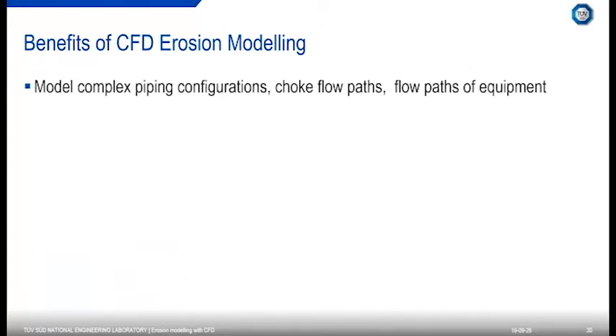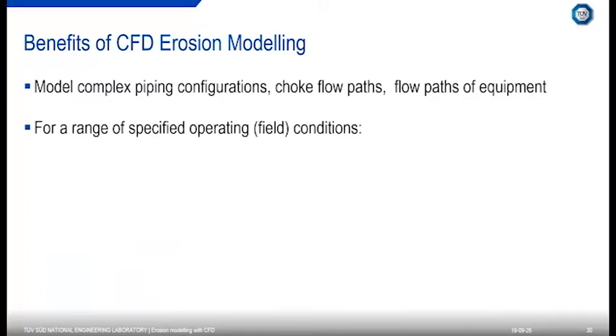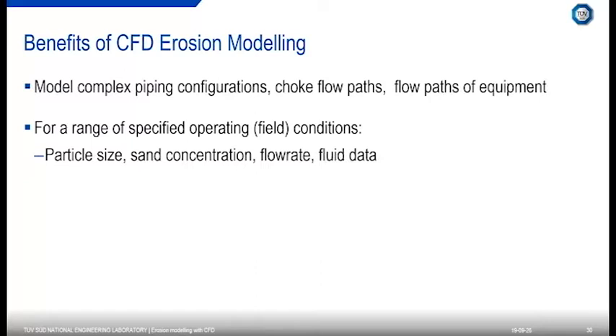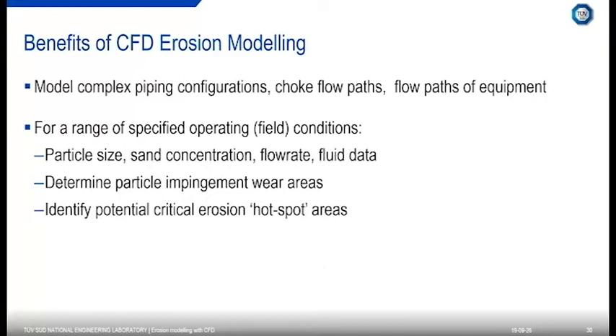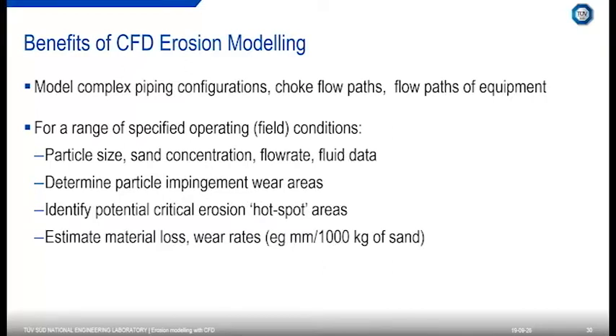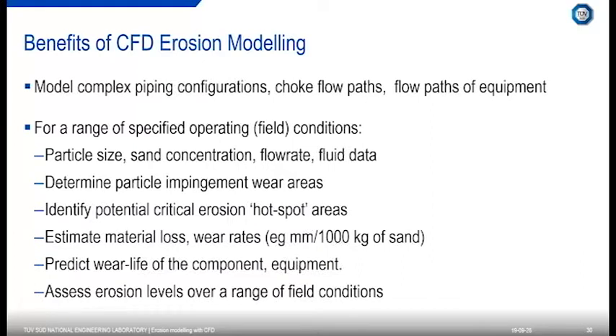So the benefits of doing the CFD erosion modeling is that, unlike simple tests, we can model complex piping configurations, choke flow paths, various other different flow paths through equipment. And we can also specify operating conditions that may be unachievable through a laboratory test. So we can look at different particle sizes, sand concentrations, fluid flow rates, different fluid data. We can get the impingement wear areas, identify potential critical erosion hotspots, estimate material loss or wear rates, and eventually predict the wear life of the component or the equipment. And this allows us to do some sensitivity studies, so you can assess it over a range of conditions.